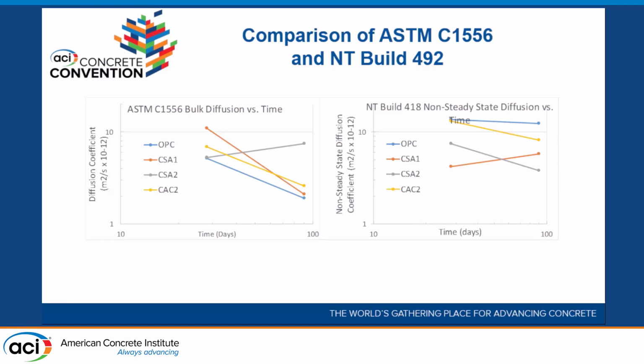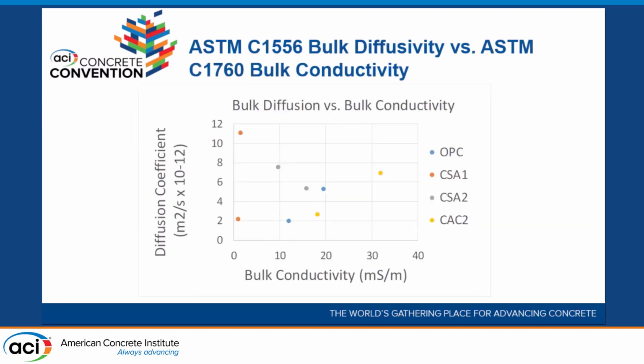So it's hard to know what exactly is going on, but we did measure these things farther out in time because they get rid of some of the early-day changes. In general, we looked at bulk diffusion versus bulk conductivity. When we ran the bulk conductivity, that was on samples that were just cured in a fog room, no lime water on them, no simulated pore water, and I think we're kidding ourselves if we think we can get exactly what the simulated pore water is for everything we're looking at.